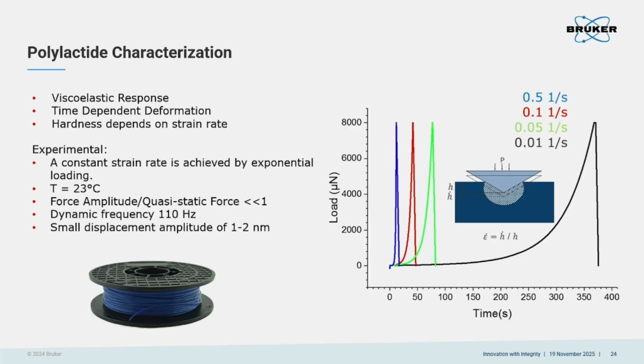So we can set up this loading rate to achieve constant strain rates. Here we apply 4 different strain rates, from a very low one, the black dots shown here. So the total time for the testing will take much longer. And we can also apply a very high strain rate to increase the speed of this testing. And the material chosen here is polylactide, PLA, I guess.